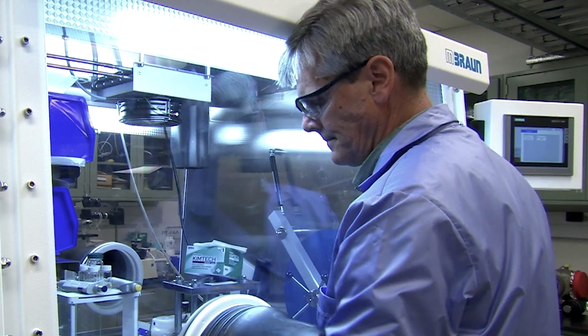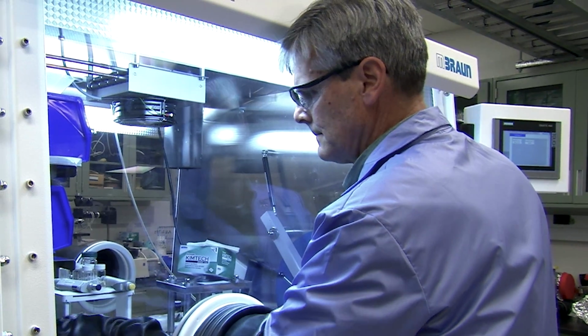In this perspective, beyond presenting the motivation for why we need to reach lean electrolyte operation and why sparingly solvating electrolytes are the way to do it, we also present design rules for how someone could select or create electrolytes with only sparing solubility of polysulfides. This redesign idea takes advantage of the fact that there's a number of constituents in the battery that have to work together. Overall, our goal with the sparingly solvating electrolyte is to essentially control the solubility of these polysulfide discharge products that we're forming, control the residence time in the liquid electrolyte for specific key intermediates, and in doing so, essentially guide or alter the reaction pathway, all with the intent of achieving high power and the high energy density that lithium-sulfur batteries promise.